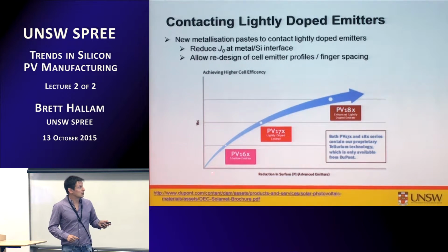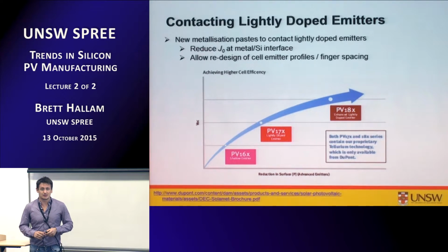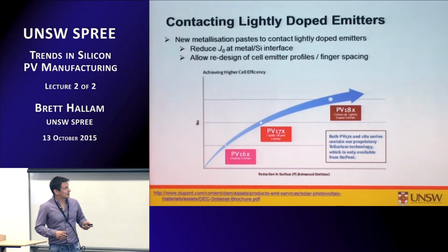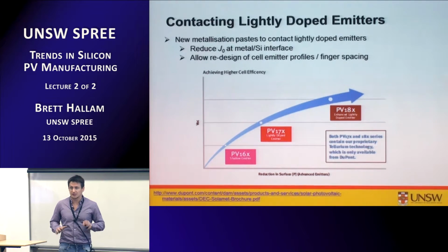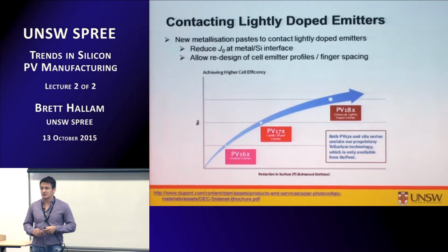So they've had a whole range of paste developed over the last 5 to 10 years, going through this PV16, 17 and 18 series that allow contact to more lightly doped emitters. So now they're claiming towards, say, 120 ohms per square that they can contact. And as we do that, we can increase the VOC of the devices. And that's been most of the efficiency enhancements have come from these developments in the last 5 years.